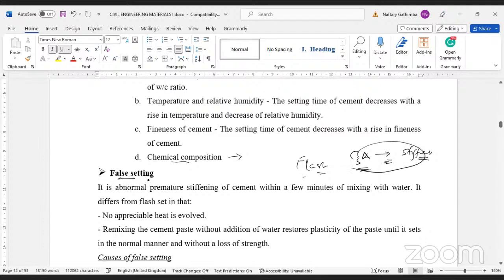However, in false setting, sometimes an abnormal premature stiffening of cement within a few minutes of mixing with water may occur. So the difference between false setting and flash setting is that in flash setting, there is a chemical reaction, there is evolution of large quantities of heat. However, in false setting, we do not have a significant amount of heat generated. And we can recover our workability, or make our cement paste workable, by just remixing without adding water, okay?